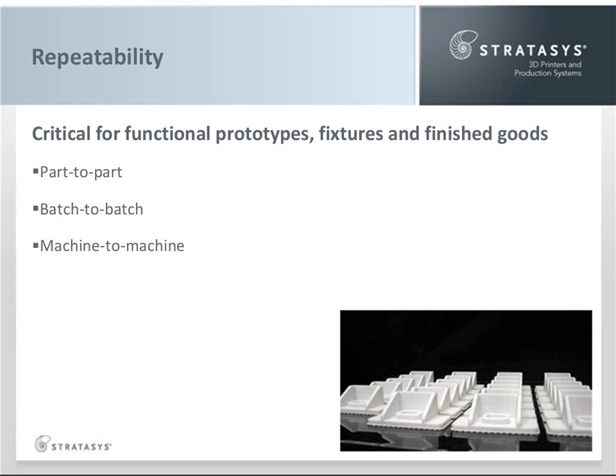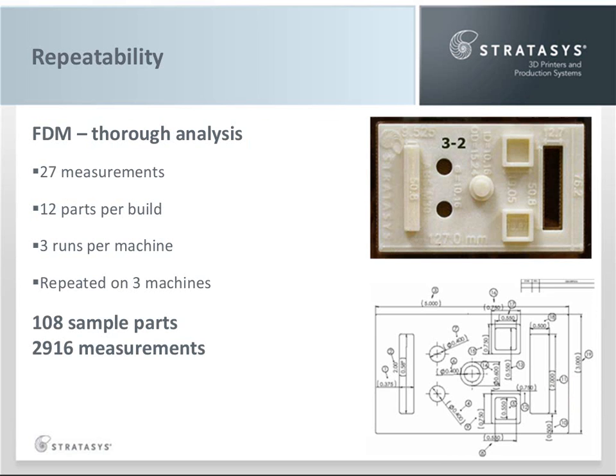But FDM is different, and I have the data to prove it. We conducted extensive studies to determine the process capabilities with analysis of repeatability. Here are the test conditions. Over 100 parts were built and close to 3,000 measurements were taken. Most importantly, no adjustments were made to the machines to dial in the accuracy. But in the real world, you would be able to use sample values as guidance to adjust controls or the model to hit target values. To do this, though, the process must be repeatable. Here's what we found.